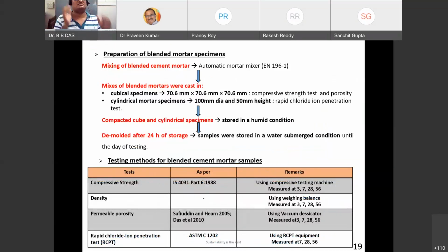Now this is the procedure for the blended specimens. This is for the mortar. We adapted a mortar mix, and the standard cube size is 70.6 mm, and for the RCPT test the standard size is 100 mm diameter and 50 mm height. Once casting is over, they are compacted and stored in a humid chamber, and then demolded after 24 hours. Now the tests we did from the mortar: compressive strength, density, permeable porosity, and rapid chloride penetration test.